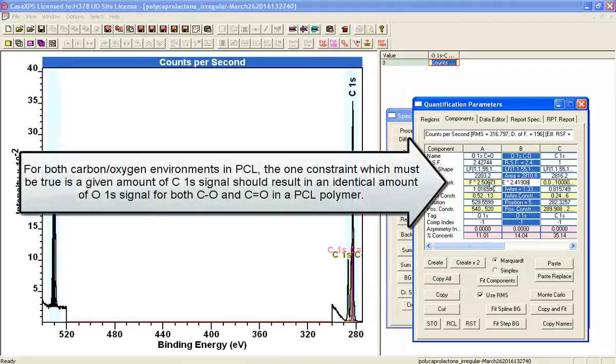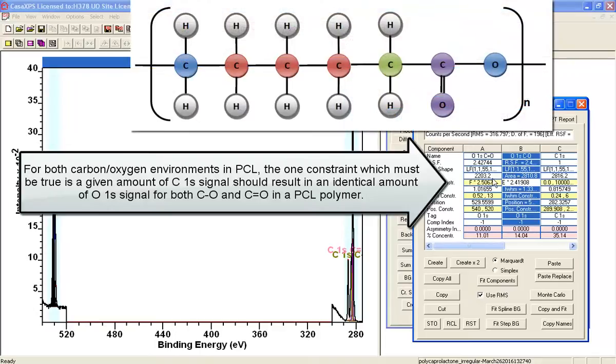The oxygen for the single bond is turning out to be different from the relationship for the oxygen to the carbon for the double bond. You need to have the same relationship for both of these because they are both signaled from oxygen and both signaled from carbon.